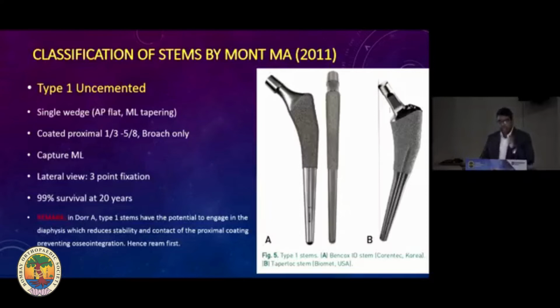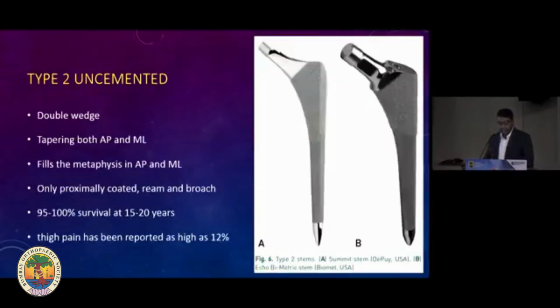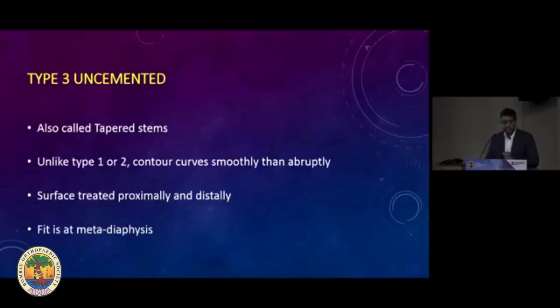Mind you, the only reason for failures in type 1 stems, that is Bencox or taper lock stems, is their use in Dorr type A canals, wherein the stem engages early into the cortex, and therefore the porous coating is not engaged with the metaphysis. In these cases, preferably ream and then hammer. Type 2 stems are double wedge, that is, mediolaterally tapering and anteroposteriorly tapering as well. Their intention is not to fit but to fill the metaphysis in the anteroposterior and mediolateral planes. It is proximally coated and uses reaming and broaching both. 100% survival at 20 years, the only problem being thigh pain in 12% of patients, an example being the Summit stem.